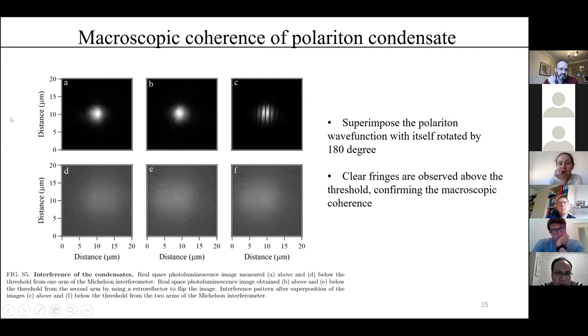This is the real space imaging of the polariton condensate in this microcavity. We also fabricated other microcavities where there is no liquid crystal. We usually observe polariton condensation trapped in very small, disorder-induced potential traps. We see very, very small red spots in the perovskite microplate. Sorry, I didn't show this result, because in this microcavity we do not use liquid crystal. But in some perovskite microplates, we believe the polariton condensate is trapped in some disorders, I think. But in this microcavity, I'm not sure about this question.